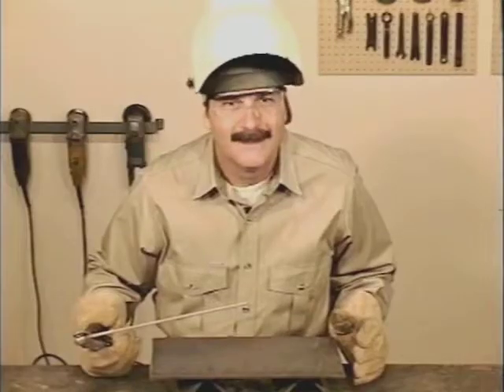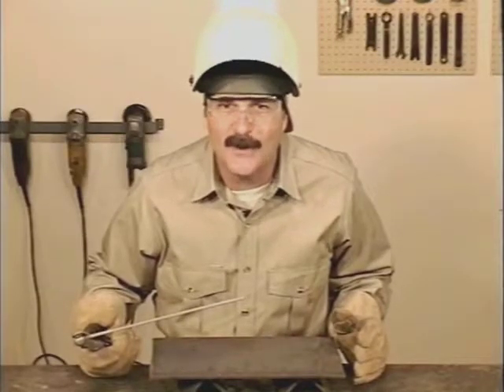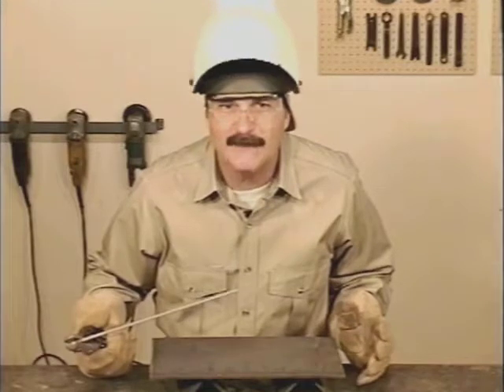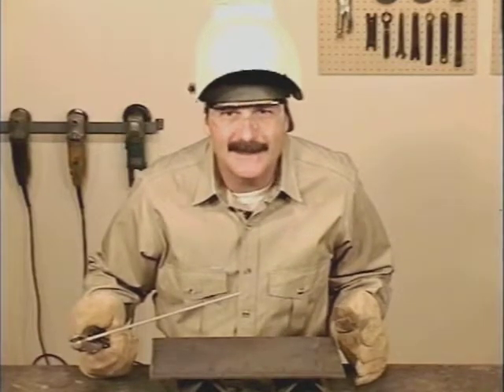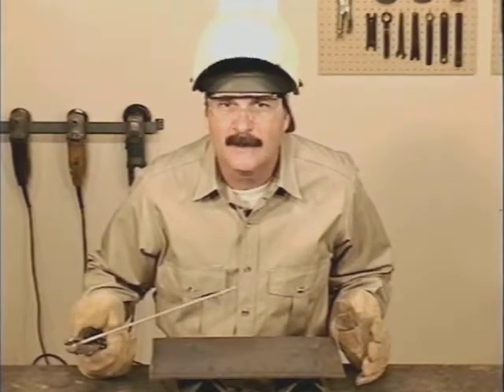If the amperage is set too high, the puddle is agitated and extremely fluid. Little balls of metal might dance off to the sides, causing excessive weld spatter. When the amperage is about right, the slag solidifies back from the rod. The sides tie in, and you can ease the puddle side to side. Here again, as you gain control of the arc gap, rod movement, and travel speed, you'll find that 7018 runs easier and cleaner with the amperage set a little to the hot side.